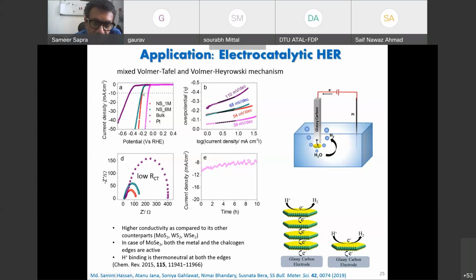Well, in case of molybdenum selenide 1 monolayer, the red one, we get about 210 millivolts onset potentials. Slightly more, 220 millivolts in case of 6 monolayer, and about 480 millivolts in case of bulk MoSe2. So, you know, this is precisely because the electron has to hop and tunnel across all these monolayers when you have multi-monolayers, but the electron has to just go across this monolayer. Intra mobility is what counts when you have a single monolayer, and that is very high, right?